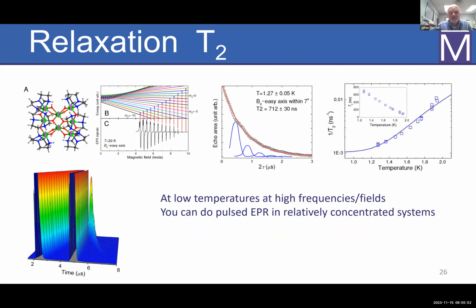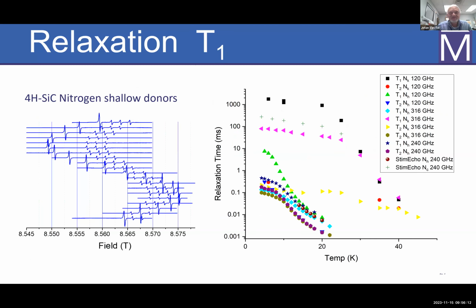So you can then even look at very concentrated systems, which is a single crystal of these iron 8 molecules that I showed you earlier. Of course, you have to be at really low temperatures to be able to even see an echo. So below 2 Kelvin, and you can see it still follows this dependence quite nicely. And I think this is going to be my last slide, actually.